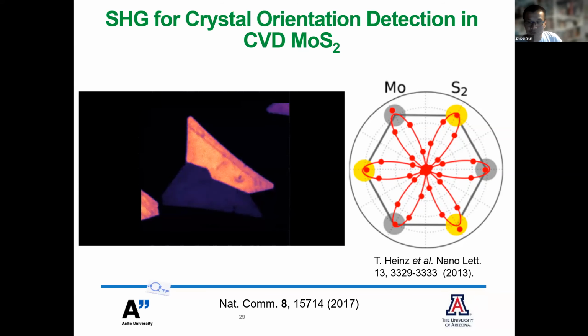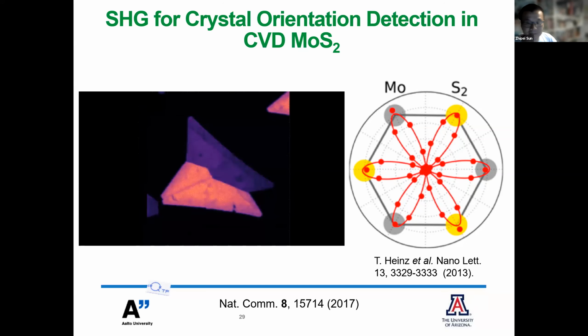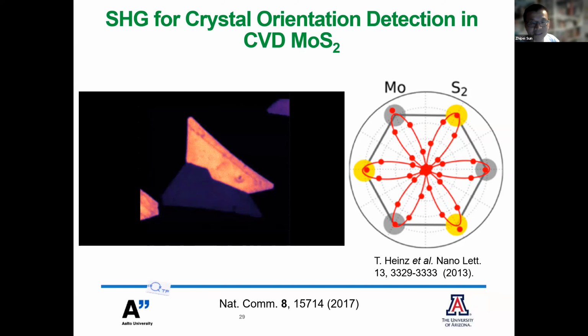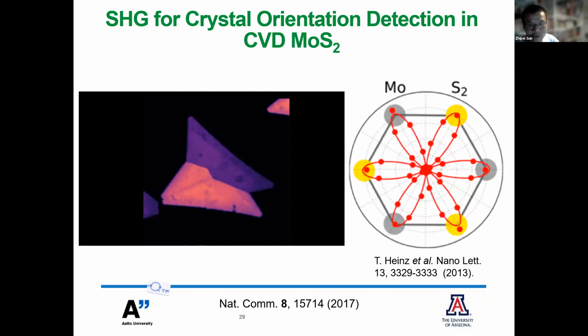So here, I would like to show you one video we take from these polarized measurements. You can clearly identify the different crystal orientations inside of one CVD flake. At the moment, this is very useful to look at the flakes, for example, if you want to make different heterostructures with different crystal orientations. And in particular, at the moment, researchers are really motivated to twist different 2D materials together to form these heterostructures with magic angle.